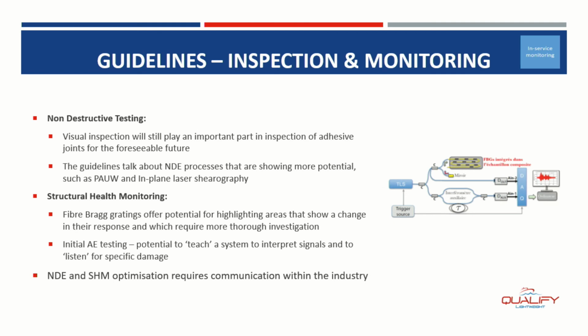The guidelines set out the protocol for validating those techniques, though. What's important is that we understand exactly what we're looking for and that we have assured that the kind of defects we think we're looking at are actually represented by the signals that we're getting back from that NDE technique. In the past, the aerospace industry have looked at things like critical flaw size. They establish a level of defect that their design can cope with, and then they look for an inspection technique that can identify that defect.